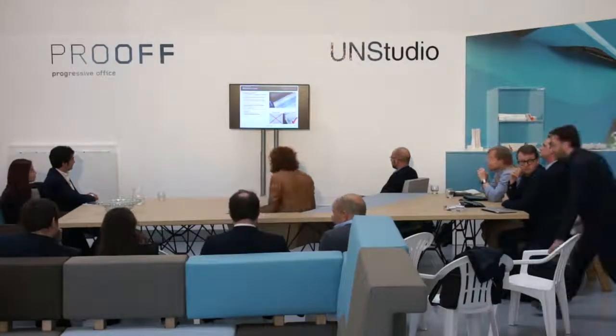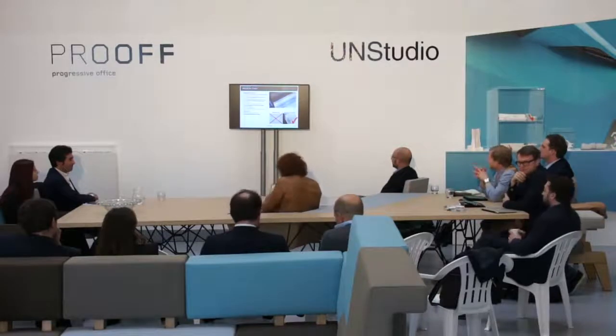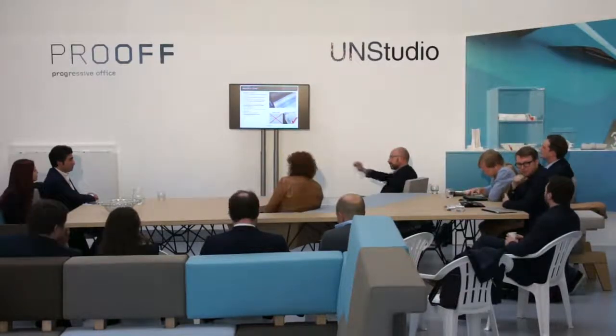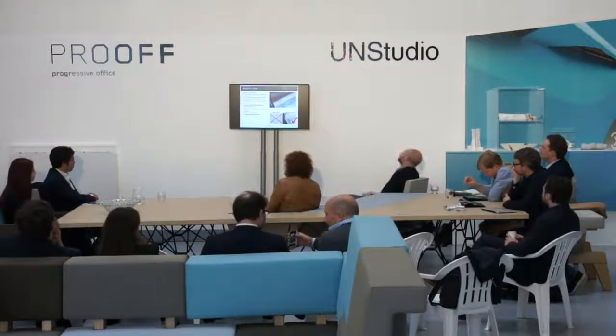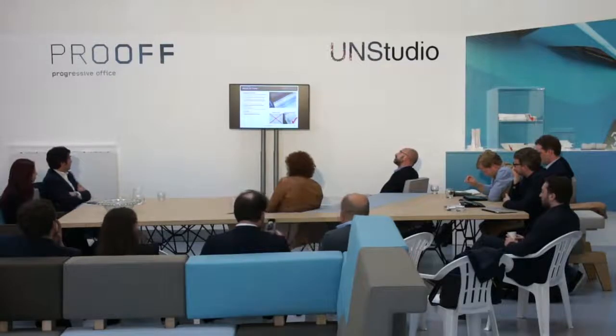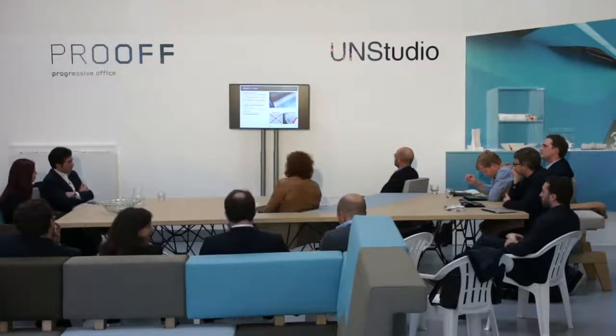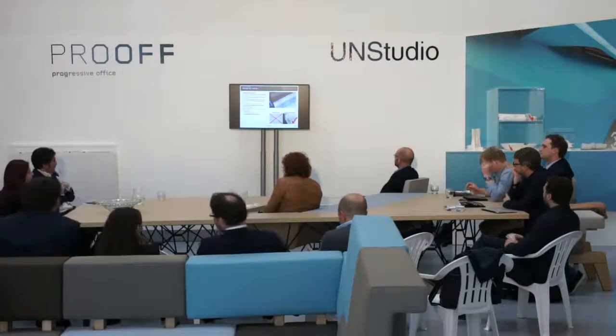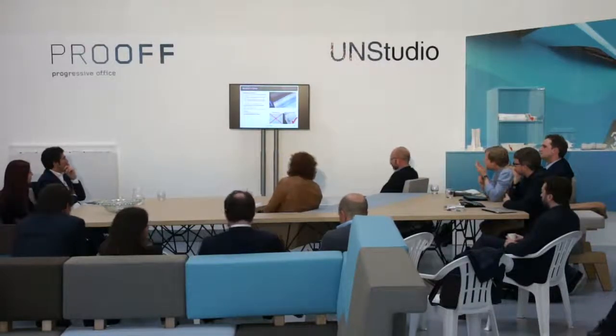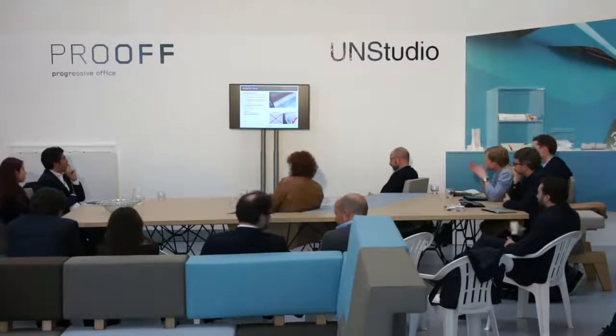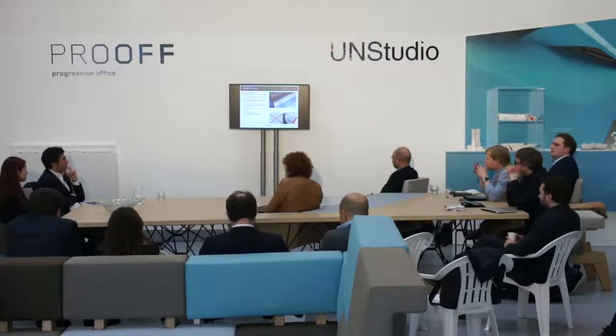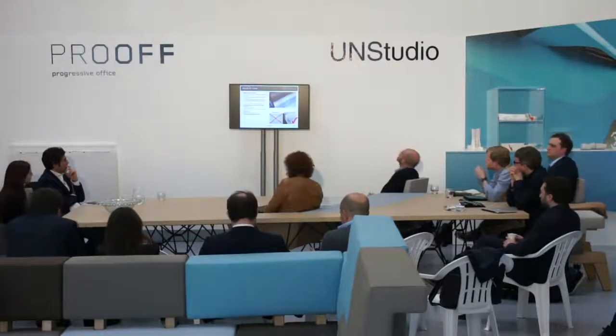The advantages, I have to really read now. The components are basically built using glass, epoxy and prepreg skins partly in the structural core, as I just said. The glass reinforcements provide a sufficient stiffness to meet all the structural requirements. The E-glass epoxy laminate thermal expansion values are very close to steel. Therefore, usually the components fixed to steel substructures move basically parallel. The cores provide the suitable thermal and structural performance. We are using only continuous fibers, no chop strand mats, again due to structural reasons.